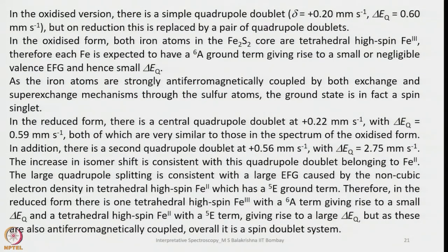In the oxidized version, there is a simple quadrupolar doublet with isomer shift of plus 0.20 millimeters per second and ΔEQ equals 0.60 millimeters per second. But on reduction, this is replaced by a pair of quadrupolar doublets. In the oxidized form, both iron atoms in the Fe2S2 core are tetrahedral high spin Fe3+. Therefore, each Fe is expected to have a 6A ground term, giving rise to a small or negligible valence EFG and hence a small ΔEQ value. As the iron atoms are strongly antiferromagnetically coupled by both exchange and superexchange mechanisms through the sulfur atoms, the ground state is in fact a spin singlet.